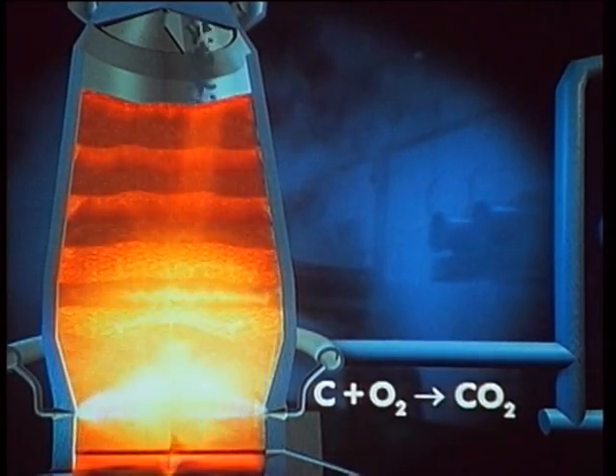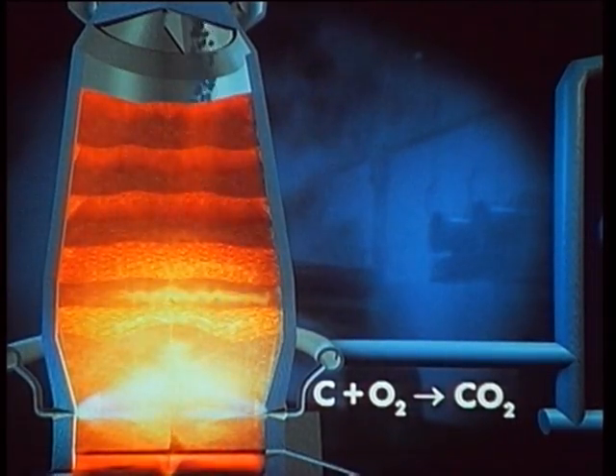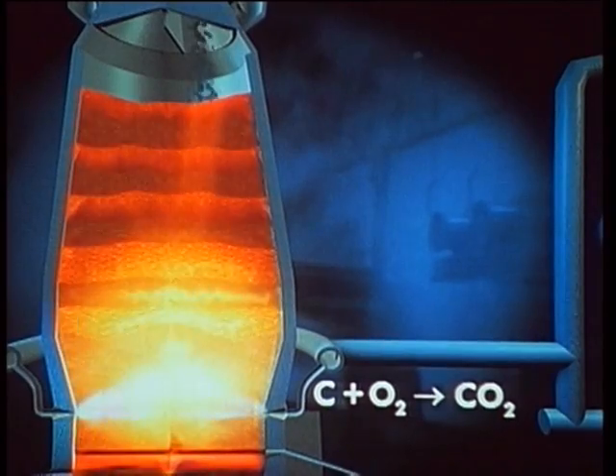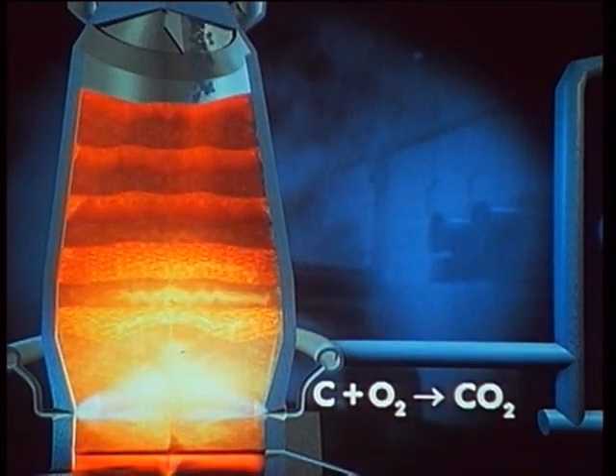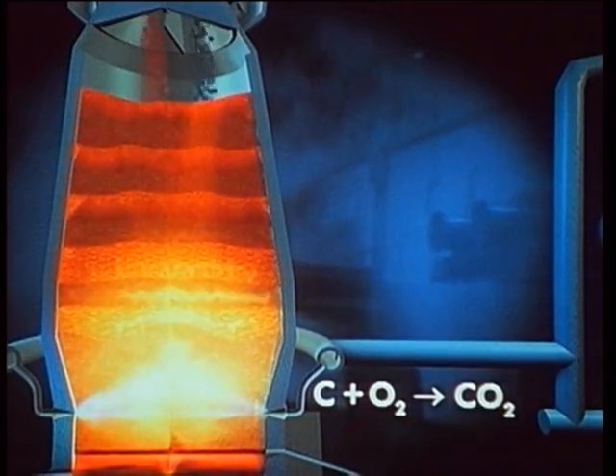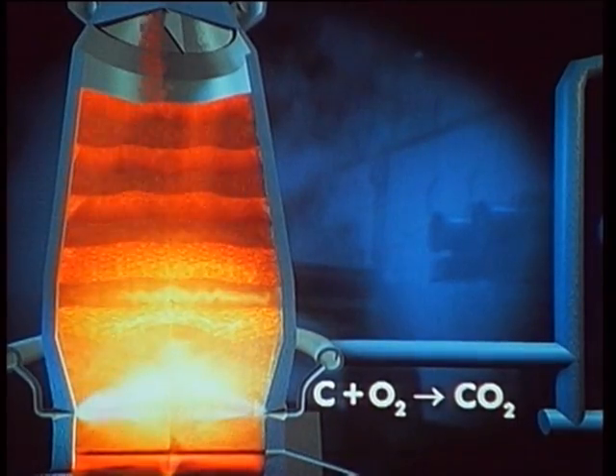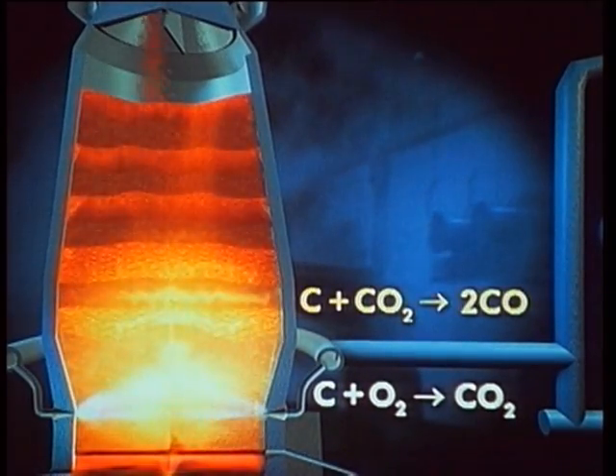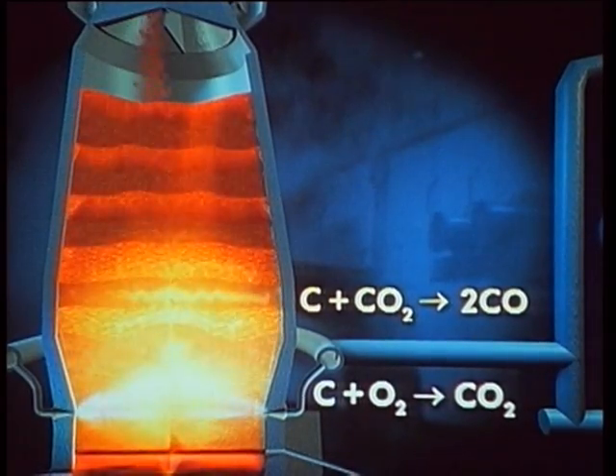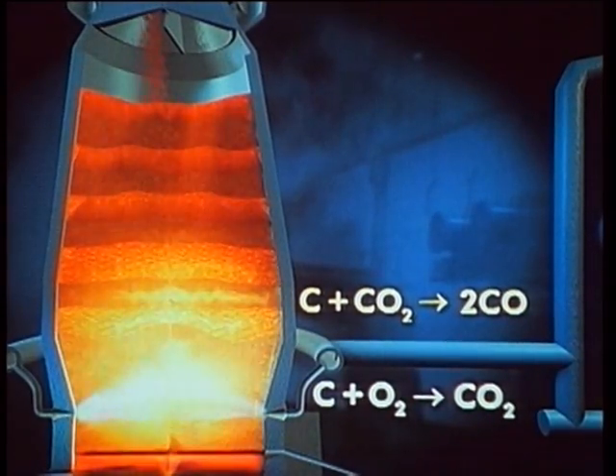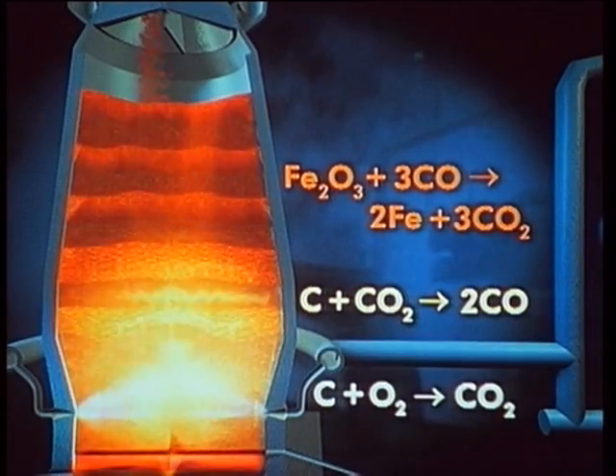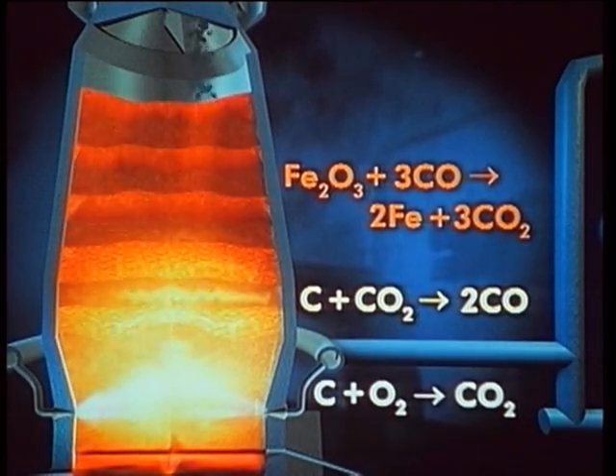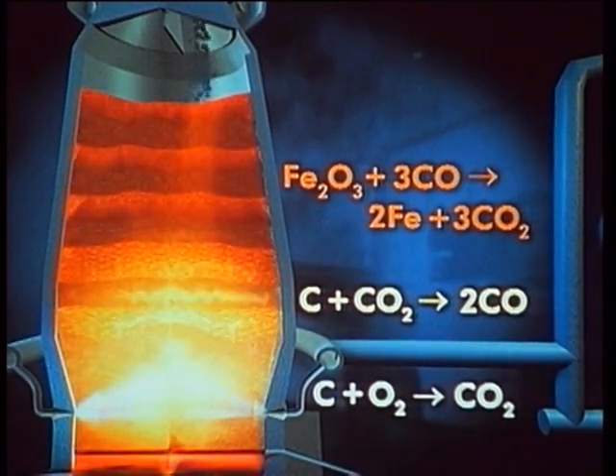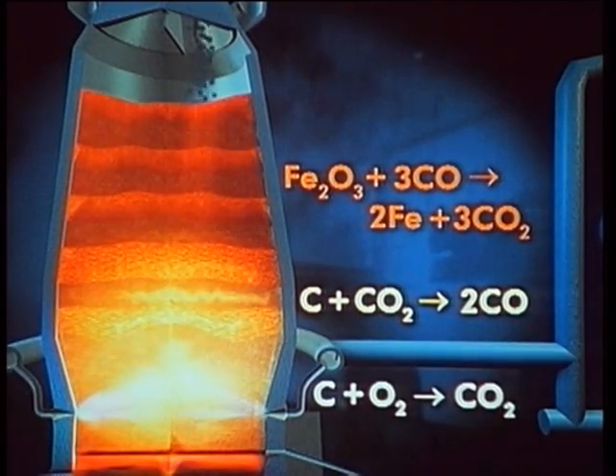The oxygen burns the coke, forming carbon dioxide. This chemical reaction provides the necessary temperature. Above it, the coke serves as a reducing agent. Carbon monoxide forms, which acts as the main reducing agent. The carbon monoxide combines with the iron oxide in the ore, forming metallic iron and carbon dioxide.